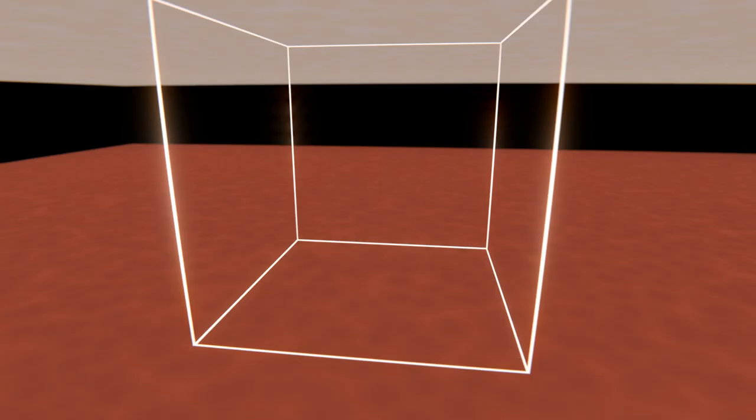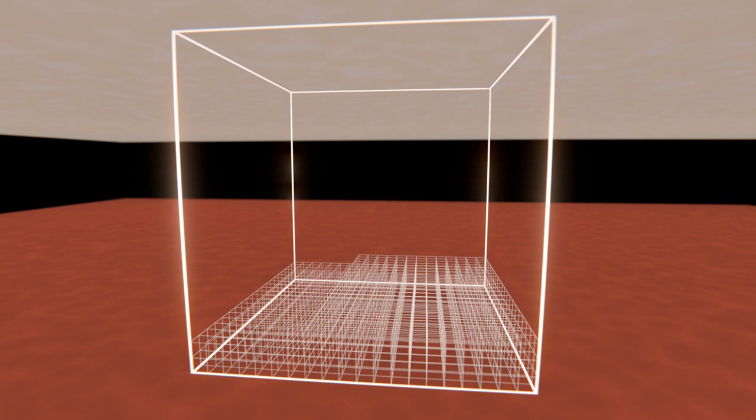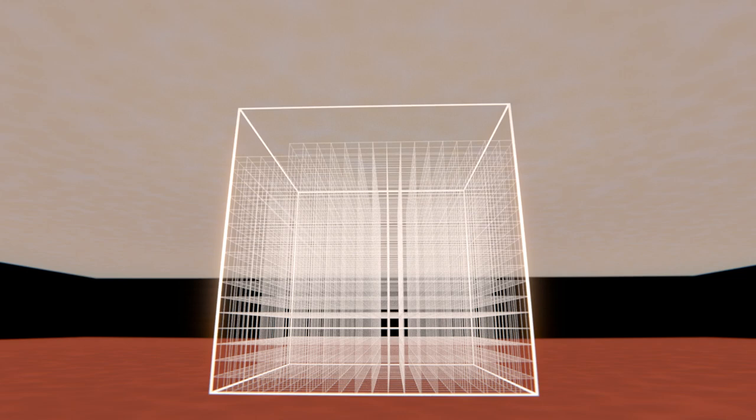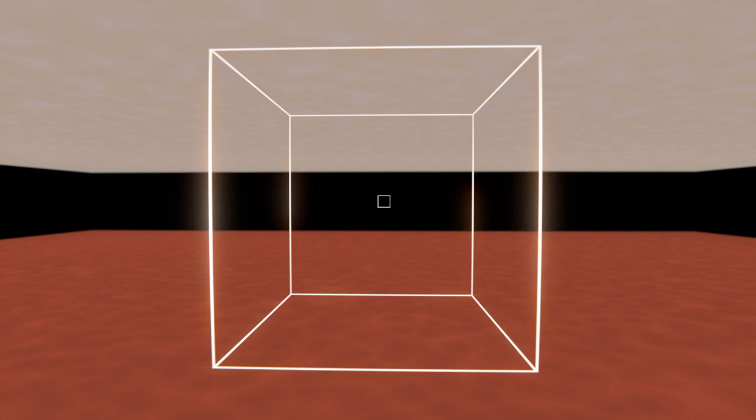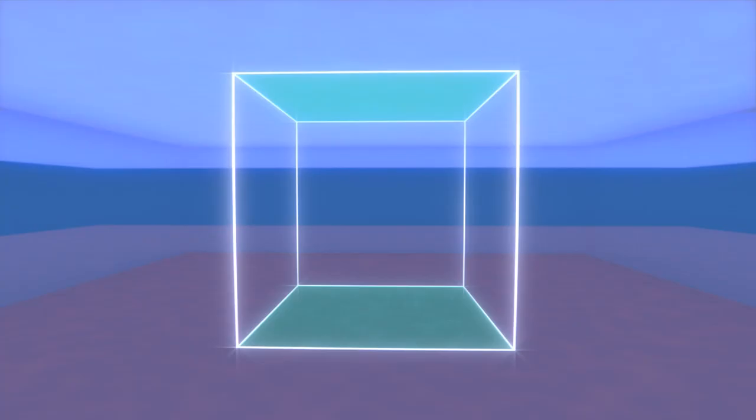A three-dimensional grid is employed to simulate the device using a kinetic Monte Carlo algorithm. The mesh cell size corresponds with the size of an oxygen vacancy. The three-dimensional Poisson and heat equations are solved self-consistently in the dielectric for each simulation step, using both Dirichlet and Neumann boundary conditions.